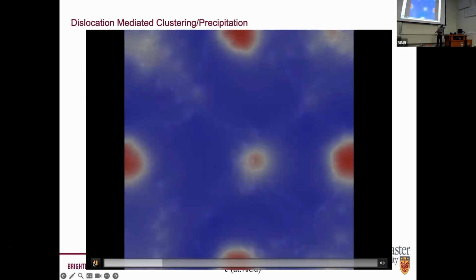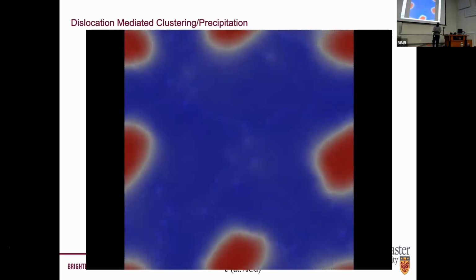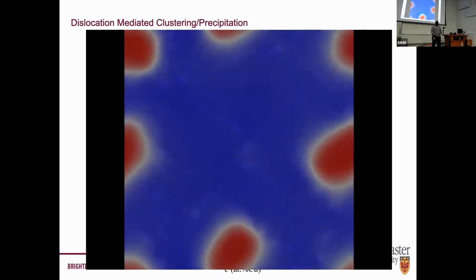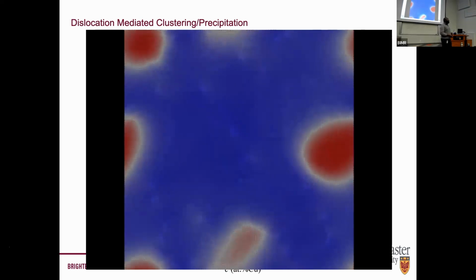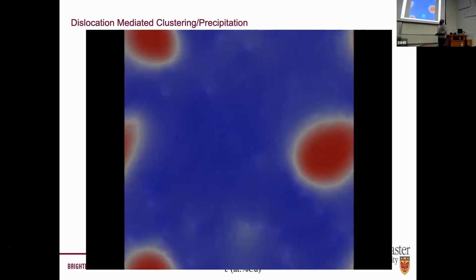And so this is my result. So the initial thing you see is my highly dislocated solid. What you're seeing here is the concentration profile overlaid on the atomic positions. Blue is low concentration, in this case, of copper. Red is high concentration of copper.